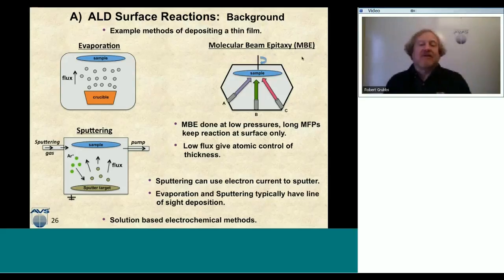and obviously we have these very low flux numbers. And so because these atoms coming out of either A or B or C, the chemical reactants onto the surface, have such low fluxes, then we do have this atomic layer control of thickness. But again, it takes a very long time to grow these samples. But what you can grow with molecular beam epitaxy are very, very interesting quantum well and superlattice structures that have very interesting solid-state physical electronic properties. And so these are three basic gas phase deposition techniques.